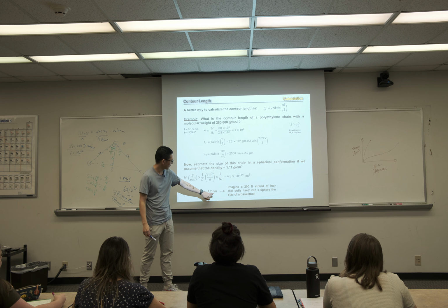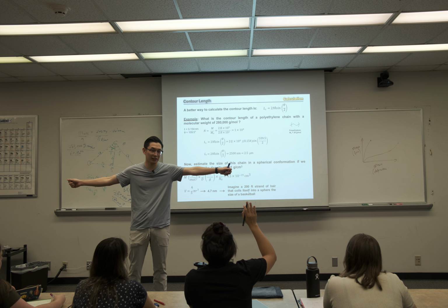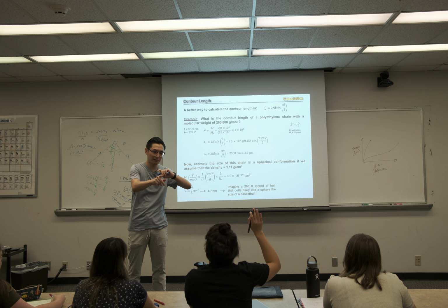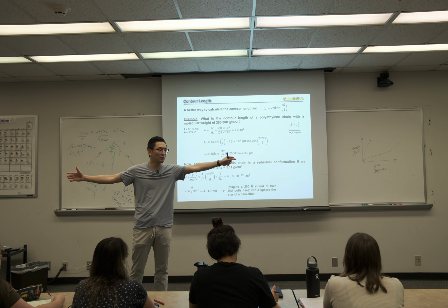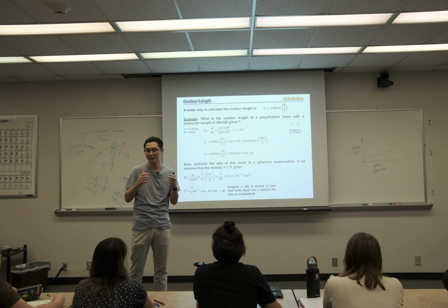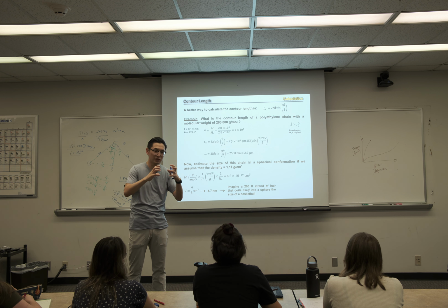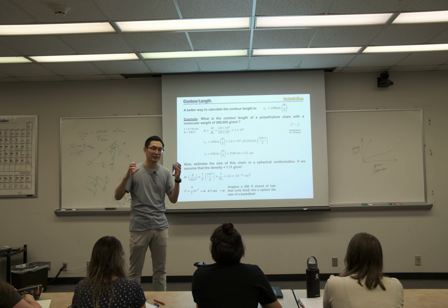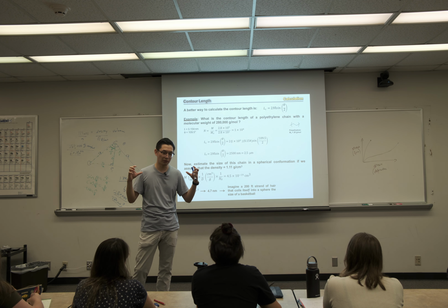So that will give you the size of the polymer chain, compared with fully stretched. We talked about fully stretched. Amy, I'll get to you in just a second. Fully stretched is micron size, right? Then we talked about fully dissolved. If it's dissolved as a Gaussian coil, it should be on the order of tens of nanometers. And you can squeeze all these chains if it's in a bad solvent. Going from a good solvent to a bad one, it's going to collapse. So your coil will collapse to a globule, and it's a dense material. There are no voids in between.